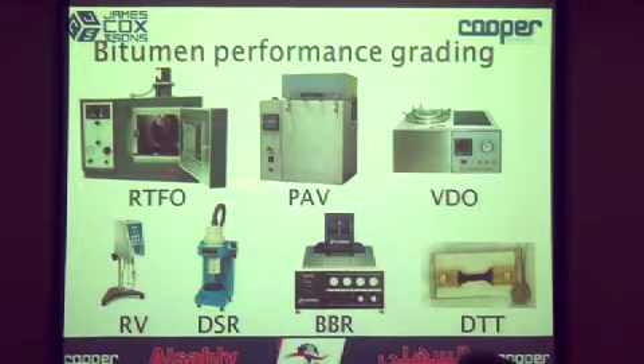These are the bits of test equipment that we have coming in the SuperPave system for the binders. We have the rolling thin film oven, pressure aging vessel, the vacuum degassing oven. The idea of the vacuum degassing oven is particularly for things like direct tension tests down here. They're very sensitive to any air bubbles you have in the specimen. The vacuum degassing really makes sure you get rid of all those air bubbles. Rotational viscometer, the dynamic shear rheometer, bending beam rheometer, and direct tension test.